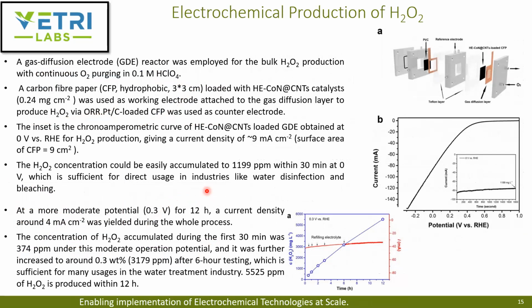Again, they used carbon fiber paper with an active area of 9 square centimeters, loaded with the combined treatment cobalt, nitrogen co-doped CNT catalyst, with a loading of about 0.24 milligram per square centimeter as the working electrode. They used platinum carbon loaded onto carbon fiber paper as the counter electrode. Here we can see the performance of the reactor, and the inset shows the chronoamperometric curve obtained at 0 volt RHE for peroxide production, giving about 9 milliamperes per square centimeter.